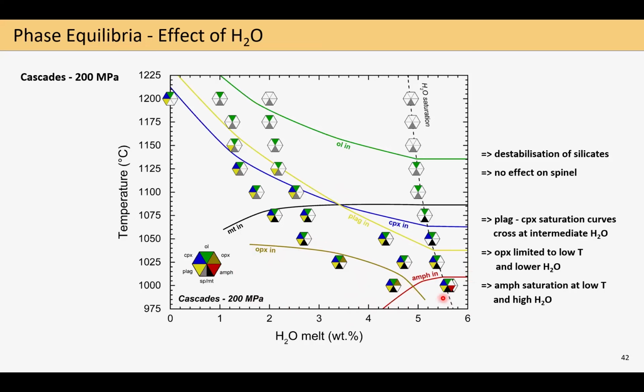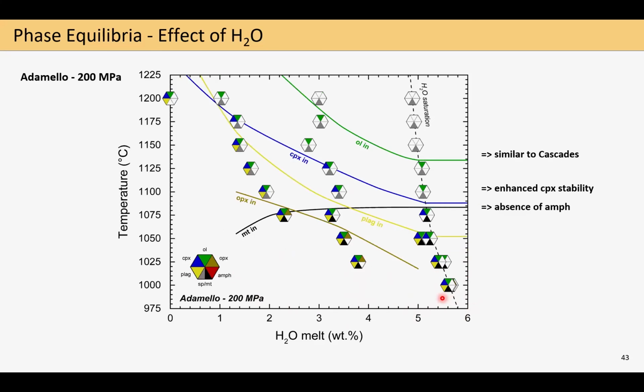And in the next step, we can compare this now to the 200 megapascal data on the Adamello composition, where the general pattern looks relatively similar to the Cascades. However, we can observe an enhanced CPX stability and, more crucially, the absence of amphibole at low temperature conditions. So here we clearly can identify the effect of bulk system composition on phase equilibria.